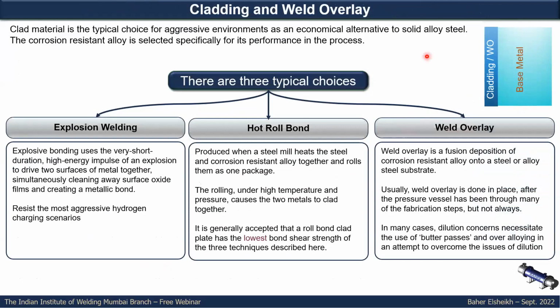And there are 3 different techniques known in the market for the application of the cladding or the weld overlay: explosion welding, hot roll bond, and weld overlay. If you have hydrogen service, you have to be very careful about selection of the type of the weld overlay or the cladding. Hot roll somehow is one of the least bonding between the cladding layer and the tube sheet base metal. That's why it is highly not advised or recommended for the hydrogen service.